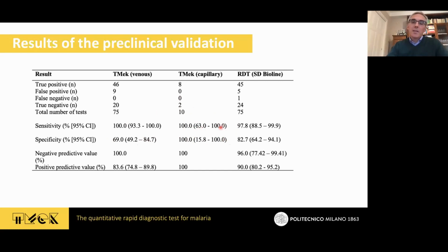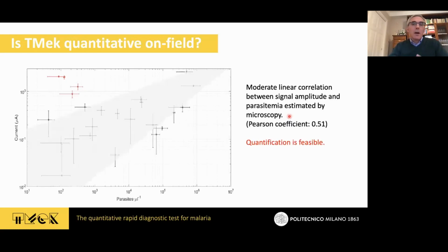And the difference probably is due to the fact that this is really a synchronous experiment. We just immediately take the sample and we immediately measure it without assisting to any deterioration of the red blood cell due to this interval between the sample and the analysis. And what is also interesting is that our performances are very comparable to well-established rapid diagnostic tests. So this is really a promising story. So I will skip this one.